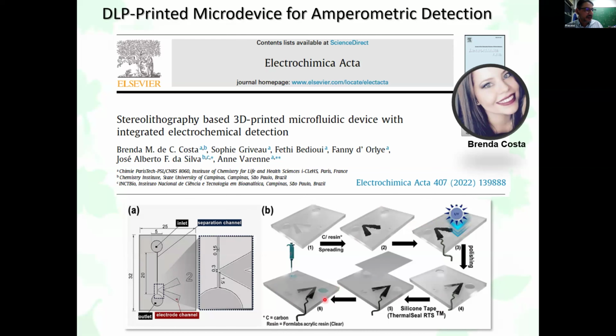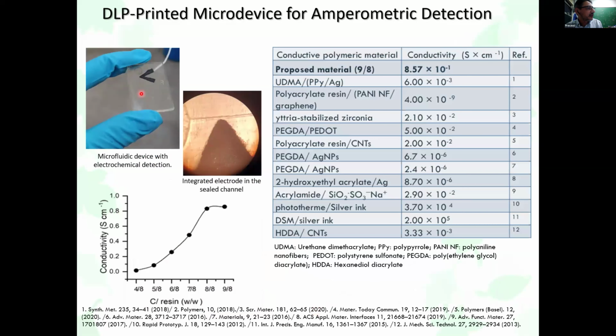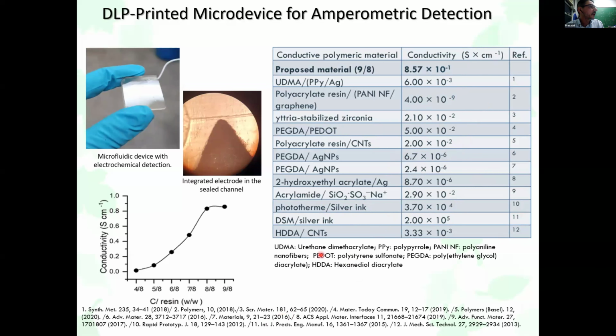So here is an example of the flow to prepare these electrodes. You can see the photograph here of the final device and the electrodes touching the separation channel. Brenda studied the conductivity of this composite material, and we got around 0.8 Siemens per centimeter. It is pretty impressive compared to the values shown in the literature, except for the metal particles, which have much larger conductivity, 10 to the 4, 10 to the 5, but it's not bad compared to many other types of polymeric conductive layers in this reference. If you need some more information, these results are published, and we can also send you more information about the reference.